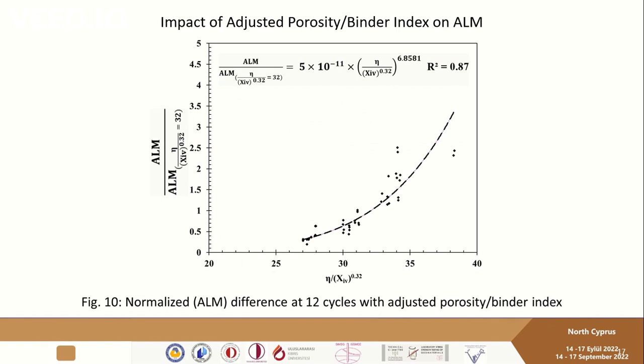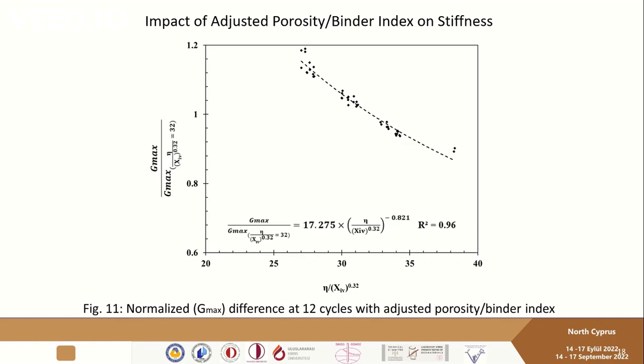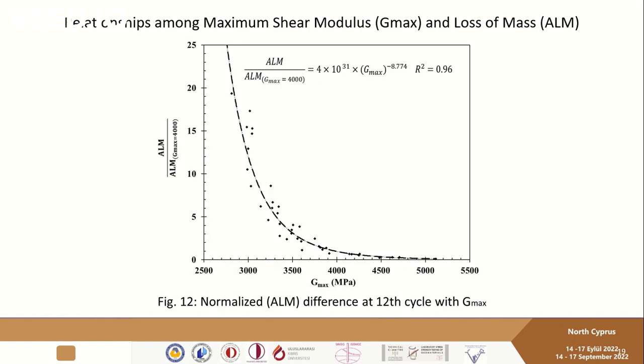Also, another important thing which was studied is the impact of the adjusted porosity binder index on loss of mass, where a relationship was found between this index and the loss of mass, and a high coefficient of determination was gotten. Also, the same story for stiffness, which is the maximum shear modulus. Also, if we come to the relationships between shear modulus and loss of mass, we can see that there is a relationship between them, and a high coefficient of determination was gotten. And as you can see, as the shear modulus increases, the loss of mass decreases too.